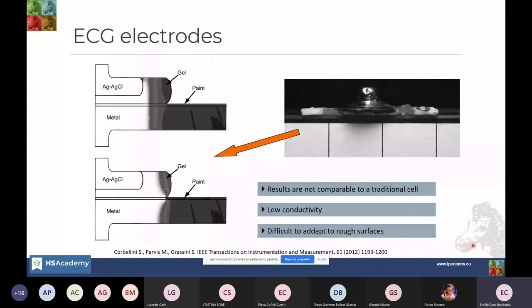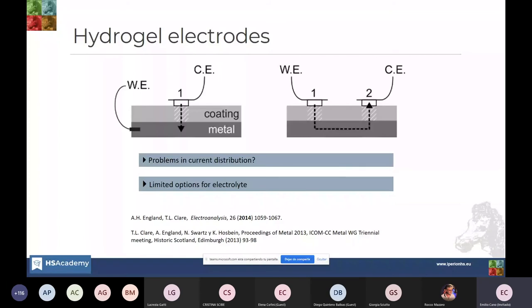Following a similar approach, another group in the United States, led by Tammy Clare, has used hydrogel electrodes. In this case, the idea is similar, but they synthesize their own hydrogels to have a better control of the system. And what is more interesting, from my point of view, more than the electrode they used, is that instead of using this system shown on the left, in which we have to attach a cable to the metal to make electrical contact with a working electrode, they propose to use a system in which they apply two electrodes in parallel, a working electrode and a counter electrode, on the top of the coating. In this way, you do not need to make an electrical connection to the metal.